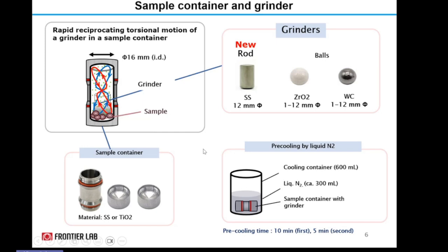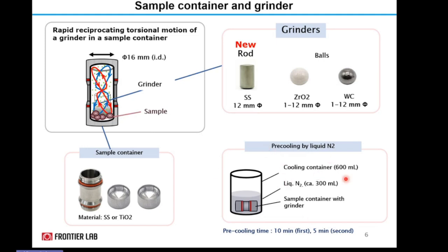On the right bottom, let me take my laser pointer. So this is the pre-cooling setup. Basically it's a beaker type reservoir which has a capacity of 600 milliliter, and you fill this with 300 milliliter of liquid nitrogen, and you immerse the sample container with grinder and sample together. Generally when we do the first cooling, 10 minutes. In some samples, since we are doing a short time crushing, we may have to repeat the cycle.